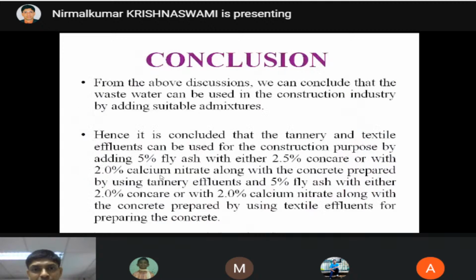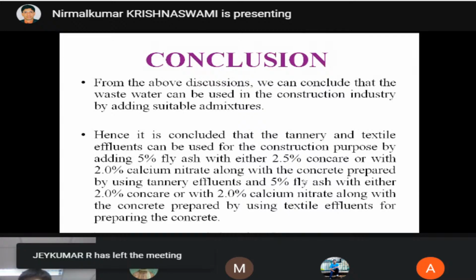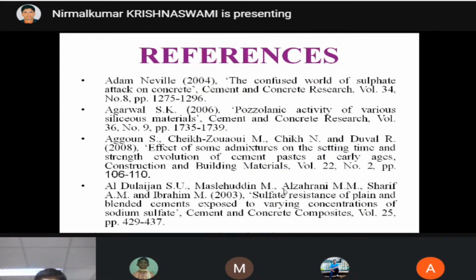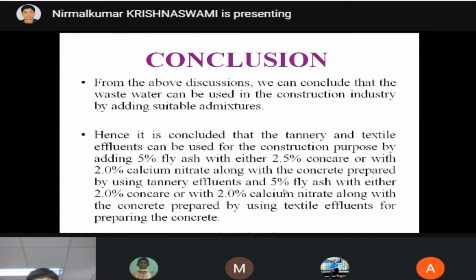So let me conclude. It is concluded that the tannery and textile effluent can be used for construction purposes by adding 5% fly ash with 2.5% concrete or 2% calcium nitrate along with the concrete prepared using tannery effluents. And for textile effluent, it is 5% fly ash with 2% concrete or 2% calcium nitrate. This is the bottom line, the message you have to take. This is our basic finding, and by using it we can easily counteract various adverse effects and use the tannery and textile effluent for construction purposes.